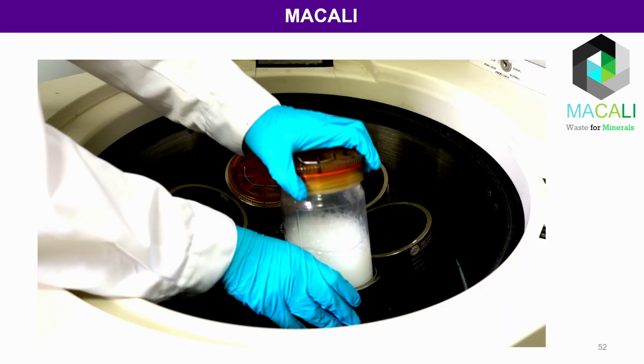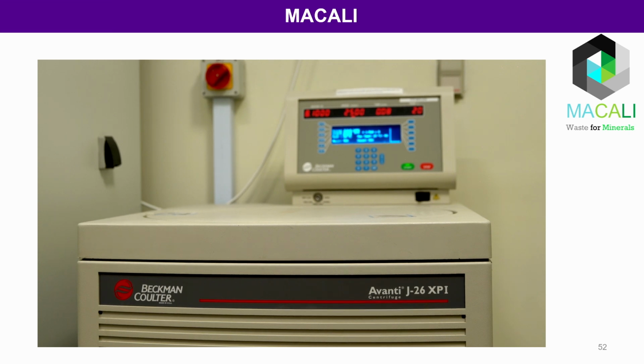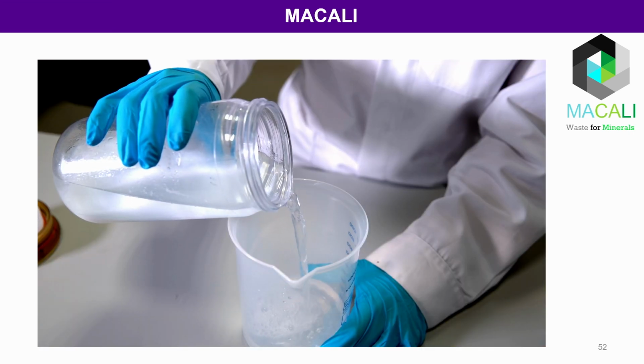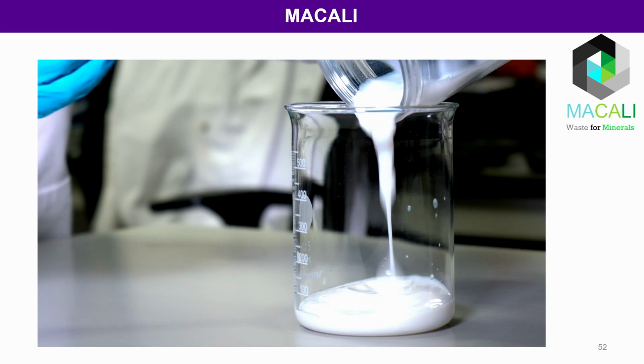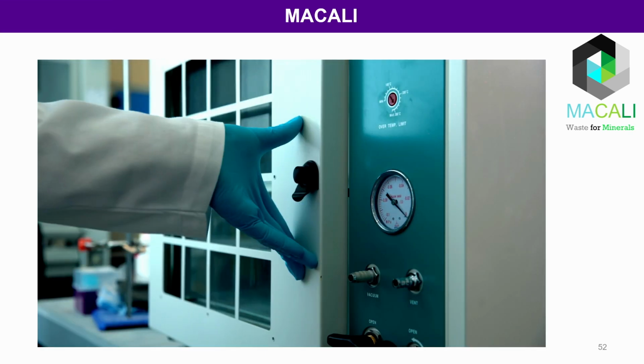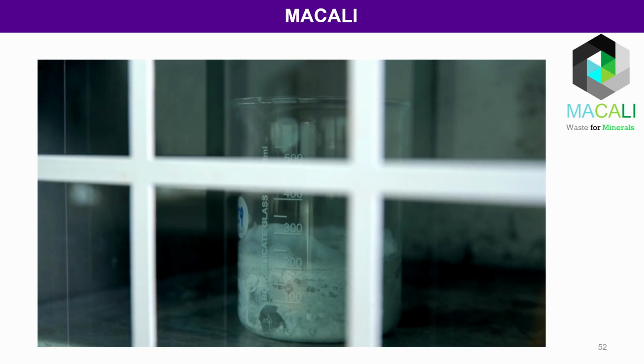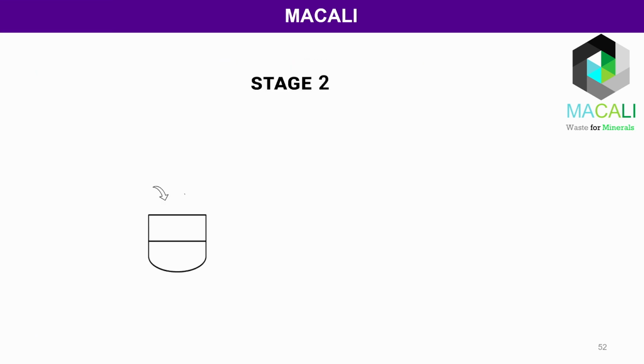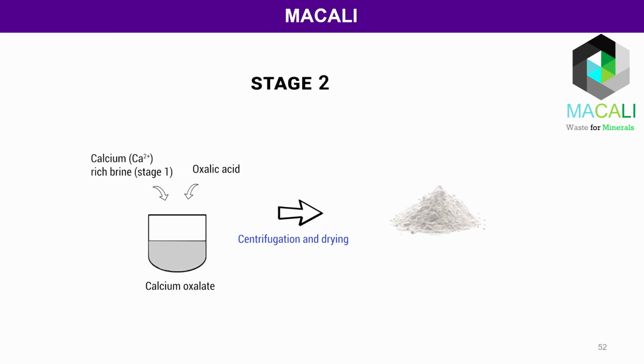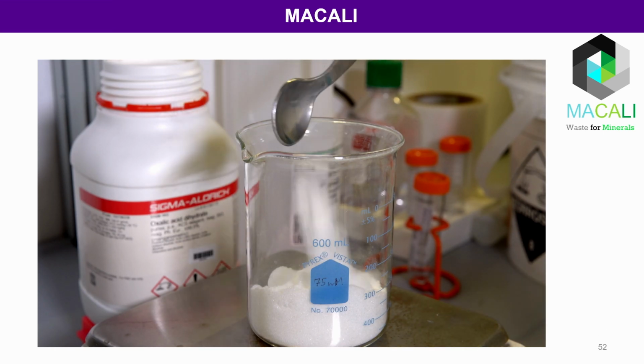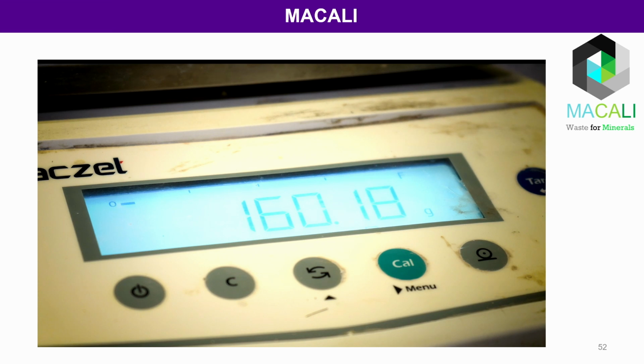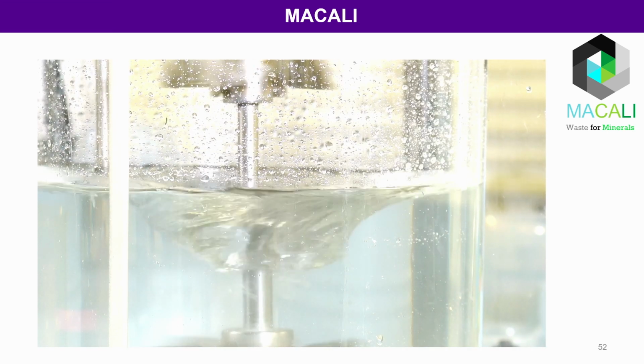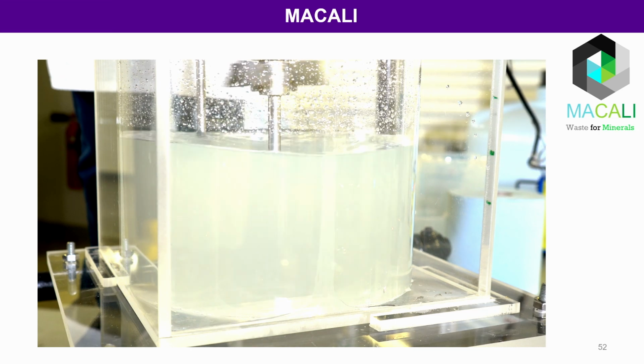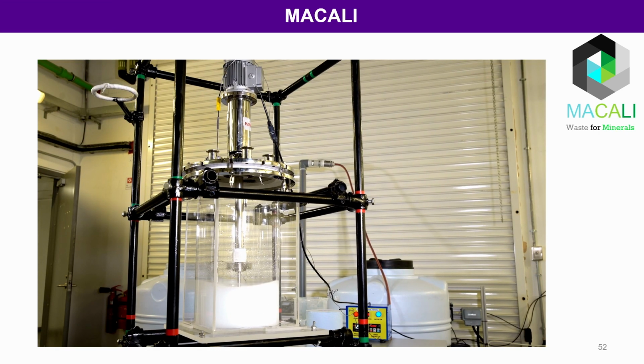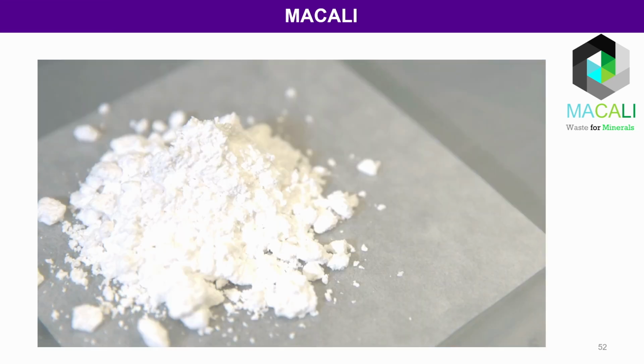Depending on the purity required for brucite, the wet powders can be washed in one or several centrifugation cycles using deionized water and achieve up to 94% purity. The wet powders are then transferred to heat in an oven at 100 degrees Celsius to obtain anhydrous brucite. In stage 2, a similar precipitation process can also be utilized to recover calcium ions in the form of calcium oxalate, a valuable mineral that uses oxalic acid as a cost-efficient precipitation agent. This process is similar to stage 1, where oxalic acid could be added directly to calcium-rich brine from stage 1 to synthesize calcium oxalate powders within 1 hour of reaction time.